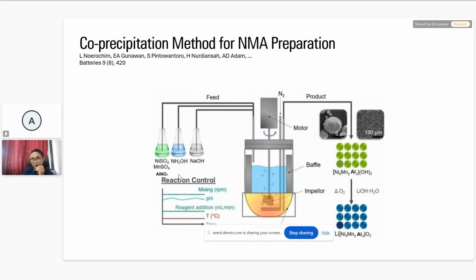Another thing we have to consider in this preparation is the volume. Even if we have already calculated the stoichiometry, people say maybe I want to try a very small amount because of limited precursor in the lab. In our experience, if we only prepare maybe 100 milliliters or 200, it is not enough. So sometimes we fail, and we cannot get the correct phase for this NMA cathode.